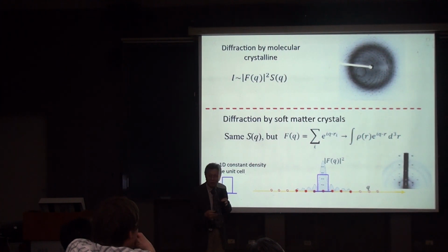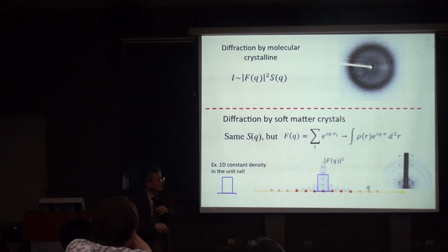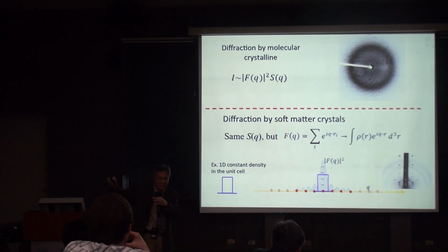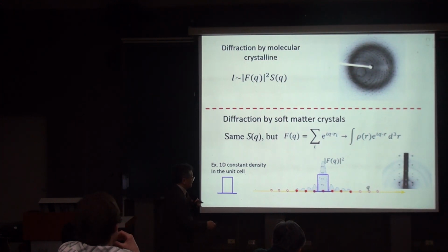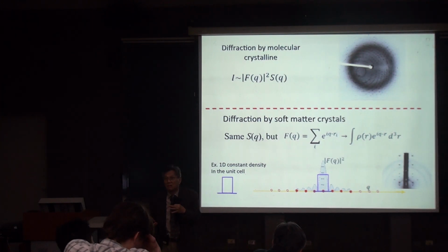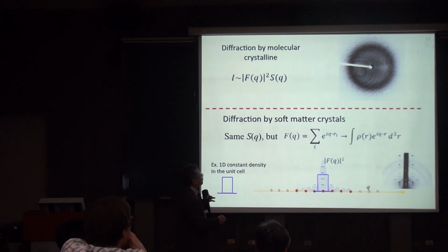But to construct the electron density, you need to solve the phase. I don't know if you have learned this or not. X-ray diffraction measures absolute intensity. But the diffraction amplitude is the magnitude times the phase. It is a phase problem. The phase problem of protein is famous, right? People solved the phase problem of protein and got Nobel Prizes. Many of them.